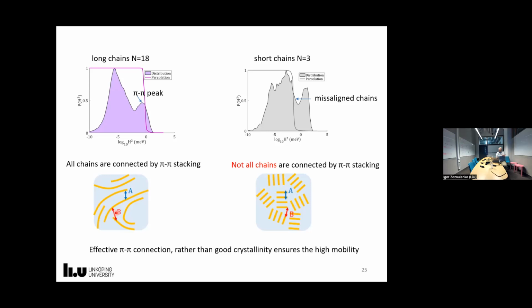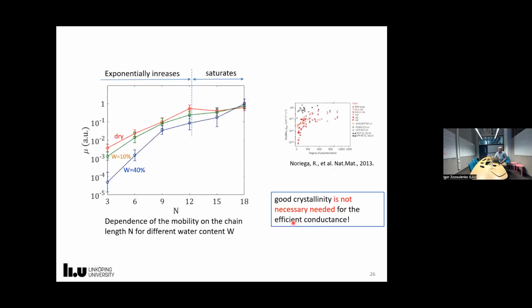If you increase the chain length, you will still have these percolative paths through the film, so it would not change much. However, if chains are not long enough, you don't find pi stacking between different crystallites. For example, here in this region, A is not connected to region B by pi stacking. Therefore, the mobility decreases, and the conductivity is not that good. Our conclusion in this case is that really good crystallinity is not necessarily needed. As soon as you achieve these percolative paths due to pi stacking between polymeric chains, you can achieve very good conductivity.